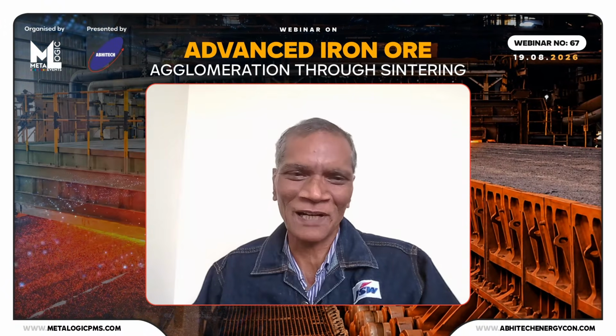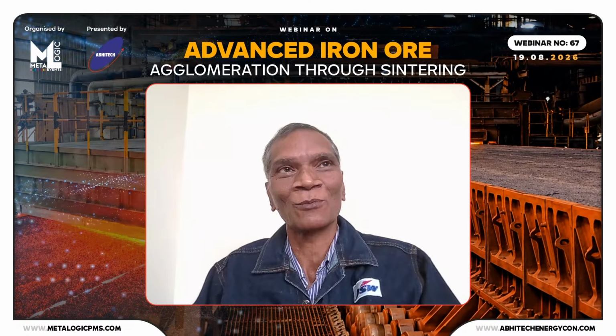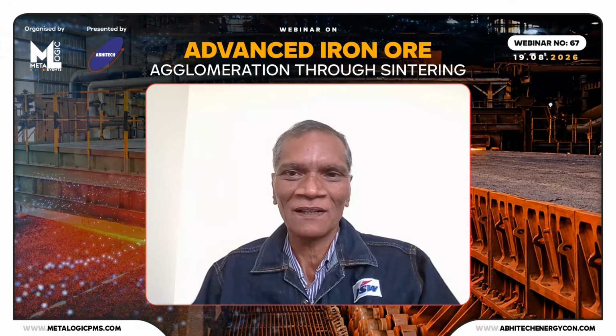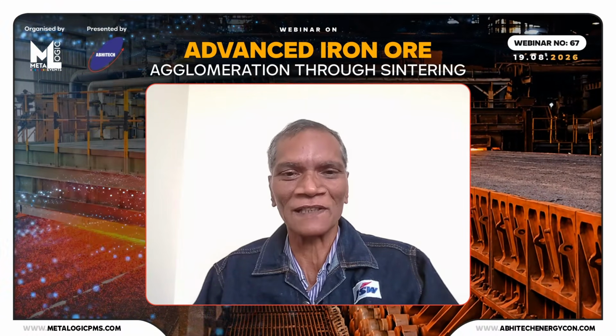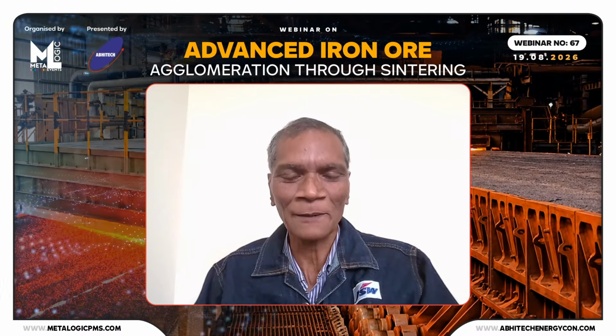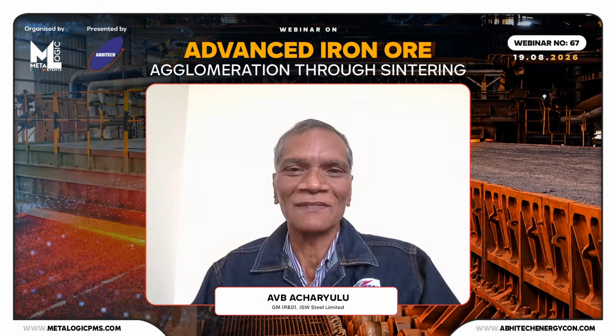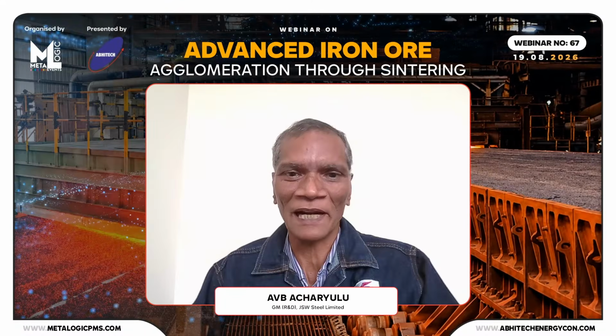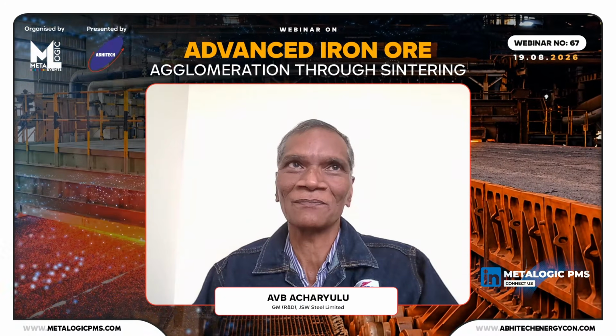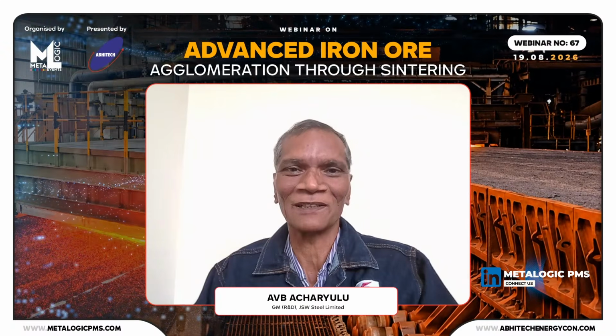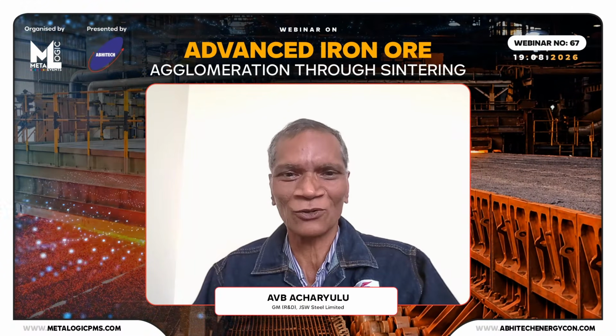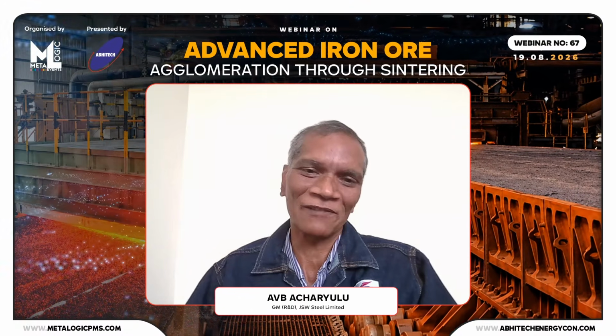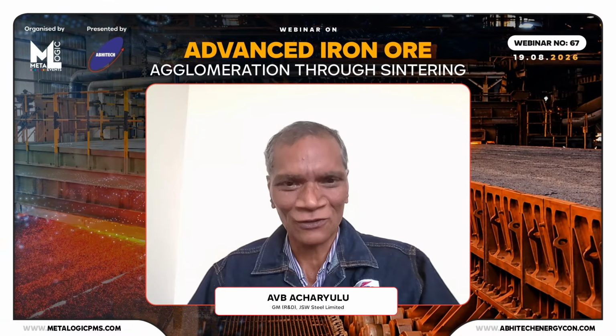On the extreme end, China has tried almost 110 kg of calcined lime and dolo put together to maximize the granulation. And in India, we are going somewhere between 20 and 60 kg per ton of sinter. Calcined lime is the most commonly used binder. Alternatively, there have been attempts to use lignin, bio-based binders, and activated binders, and players like BASF, Bhushan, we have great experience of trying those binders. There are various results coming through alternate binders also.